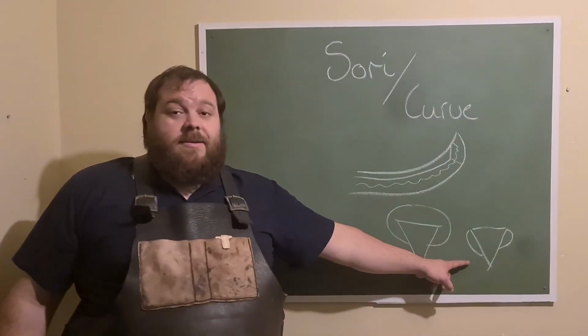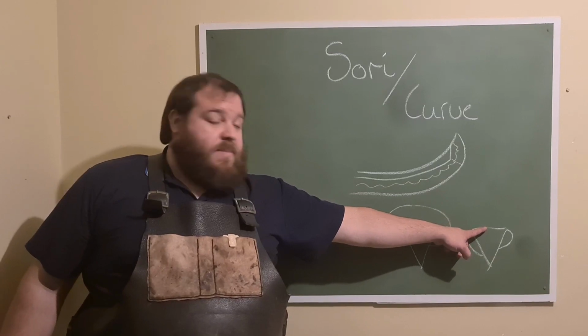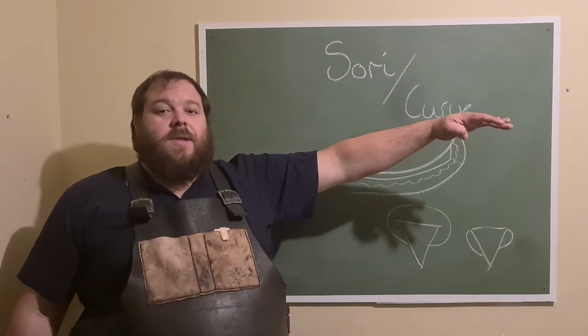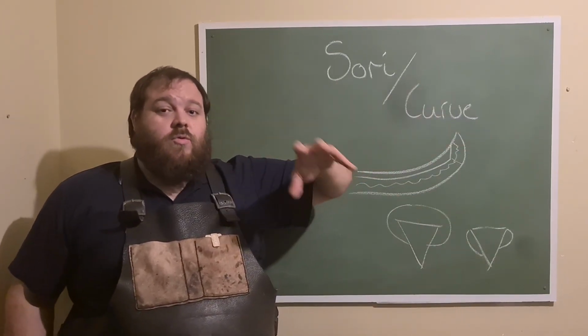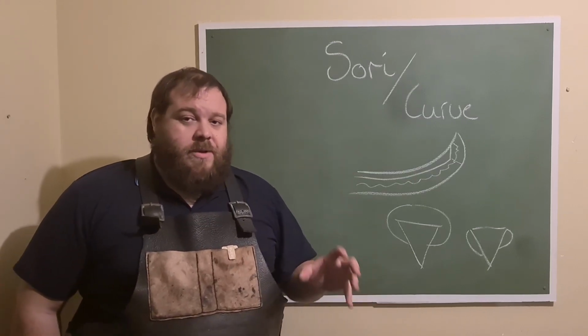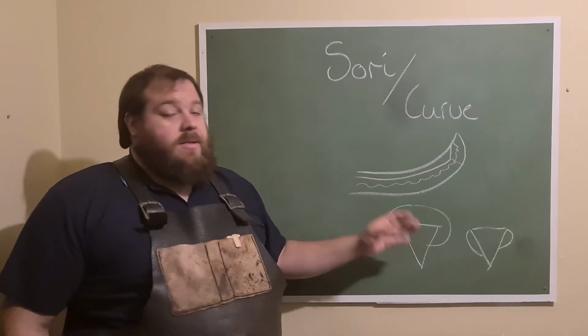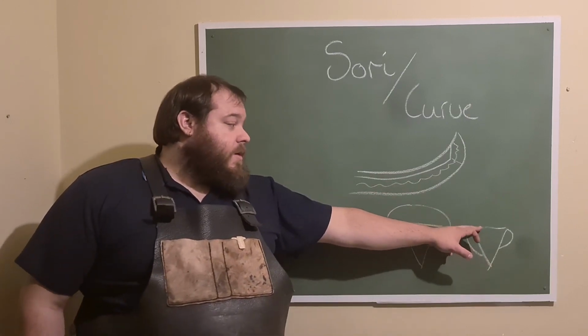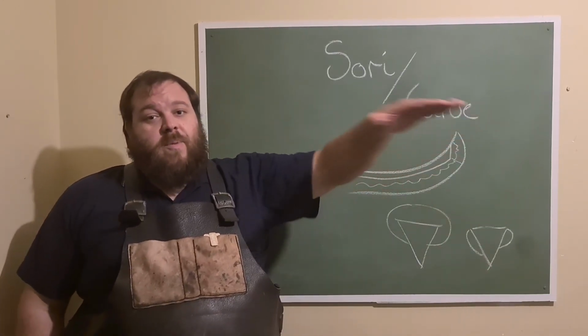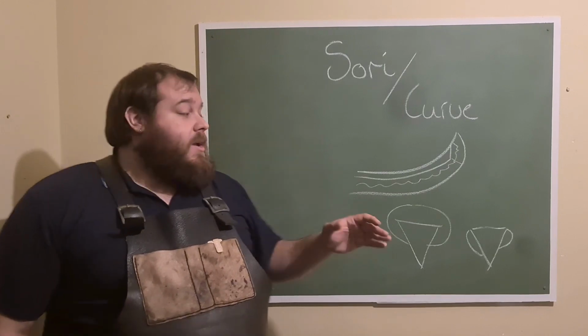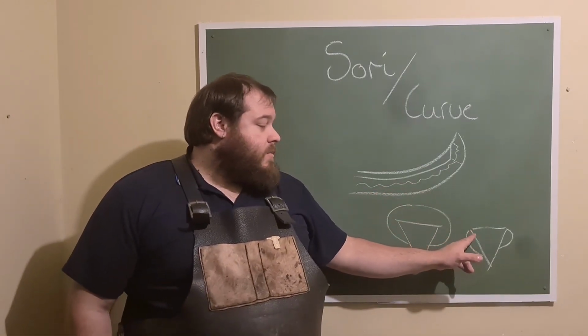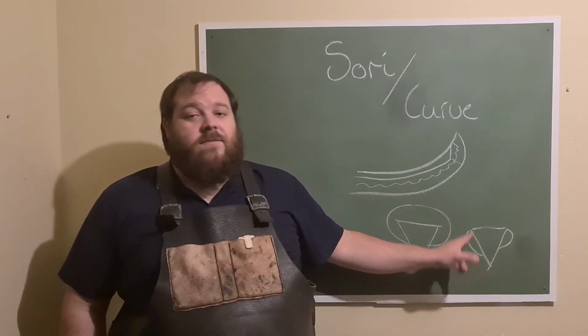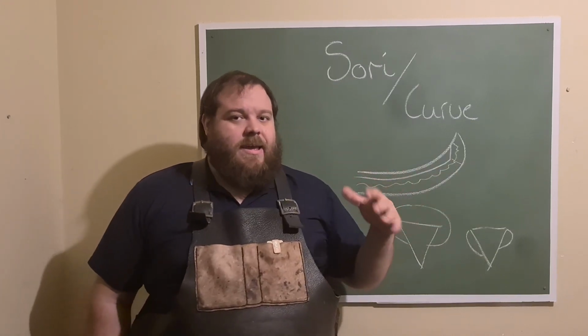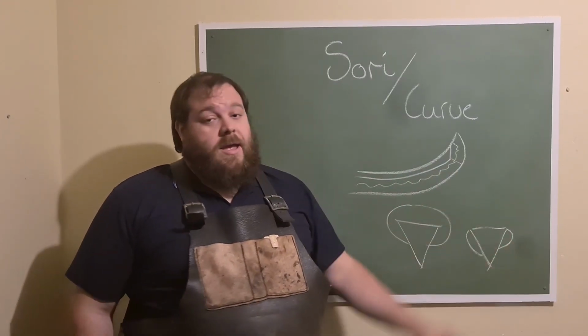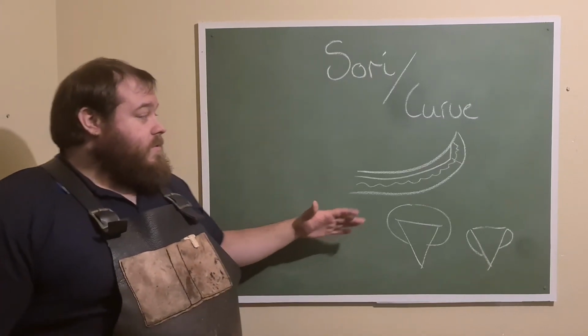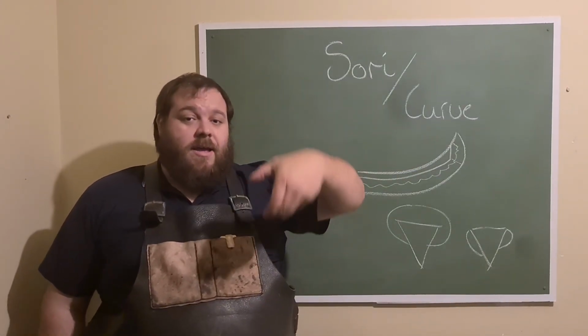That is all that is needed. As long as the spine, the absolute back of your blade, is accessible to the quench media, whatever quench media you're using, you will end up with a straight blade because there will be a hardened portion along the spine of your knife. Now, this may create a counter Hamon, which means that the Hamon may creep down the edge of the spine of your knife, but that is not as likely as you'd think, and it will stop any sori. Which is why if you want sori in a katana, you need to have the clay encompass the entire